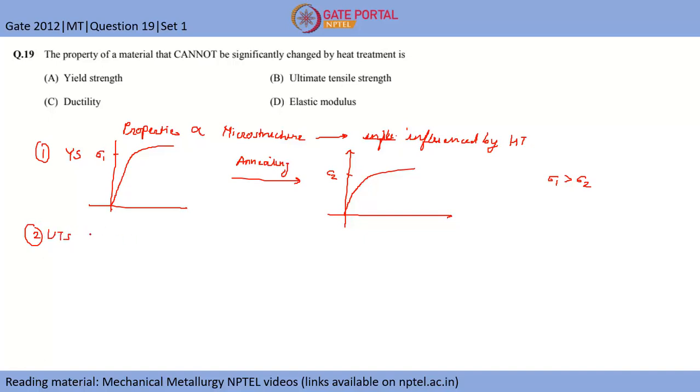Here let's say by a heat treatment, we grow some precipitates inside a material. So what it will do is the dislocations which are moving plastically, giving the plastic deformation, will interact with the precipitates, and will give you a higher work hardening rate. So this n is basically the work hardening exponent. So this n will increase with heat treatment.